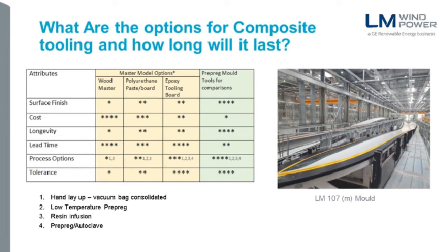So if you CNC an epoxy tooling board mold and you put it in a normal environment of prototyping, then after 6 to 10 uses or components out of that mold, it will start to deteriorate, start to crack and lose corners and lose its integrity. Whereas if we go to prepreg or epoxy mold tools as a comparison, I've heard 1,000, 2,000 prints or components out of composite tooling with a minimum amount of repair and care of those tools throughout that life cycle.